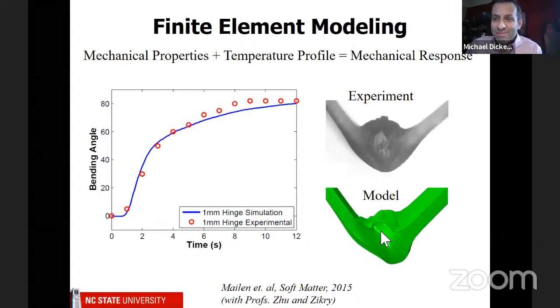And if you're being a little bit skeptical, you might wonder, well, why is the model not symmetric? Why wouldn't it be perfectly smooth? And the reason is that when the sample folds up, its thermal environment actually changes. It's no longer in contact with the substrate. It comes up, and now it's in contact with the air. So we actually can pick up on that asymmetry, well, it's not simple, but by using this model.